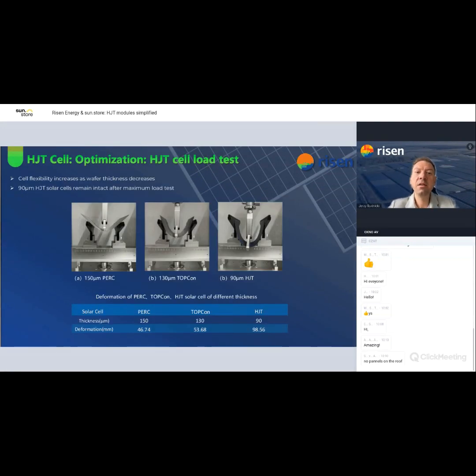And then we have been testing this, and here you could see some pictures and results from the test. So we are basically deforming the cells, the PERC cell, the TOPCon cell, and the HJT cell. And this is the maximum deformation that we achieved before the cell is fractured. And as you could see, the HJT can be bent to a largest extent out of all those three technologies, which proves the fact that the elasticity is increased, and these cells are less susceptible to micro cracking.